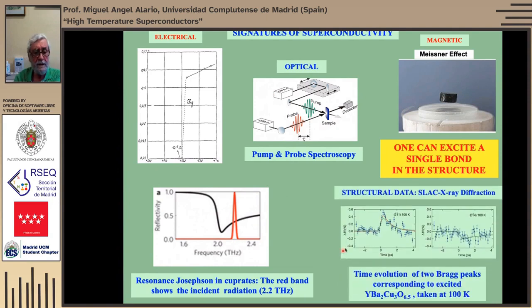Okay, so the interesting thing, this is the work of Cavalleri in Hamburg and in Oxford. He's an Italian physicist that is professor in both Hamburg and Oxford, which is most unusual. Well, besides doing the spectroscopy, they have done diffraction. They use the SLAC, which is a machine to do instantaneous X-ray diffraction, and this is in California. I cannot really describe it, but here you can see that when you make this pulse, you get this absorption spectroscopy, but you also have an effect in the X-ray lines.